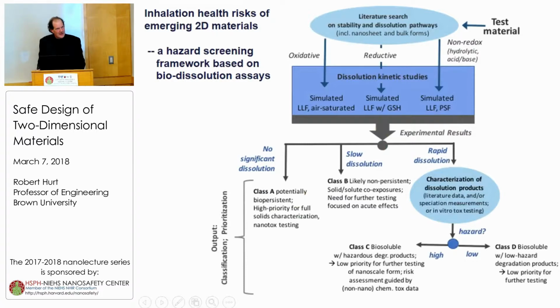And if it's rapid dissolution, you can imagine that our interest turns away from the solid to the nature of the dissolution products. And this is now a chemical tox question. It's very different. And now what is the hazard associated with these dissolution products? And maybe we know that already from the literature. Maybe we find it out by dissolving the material and doing in vitro studies. But by one method or another, using simple techniques, we could classify this further as either low or high in terms of the hazard associated with the dissolution products. And if you have low hazard dissolution products, we would call this a class D material, biosoluble with low hazard degradation products. And an example of that material would be our molybdenum trioxide 2D nanoribbons.